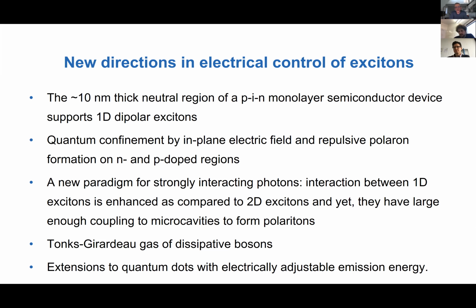If you have 1D excitons, the interaction is dramatically enhanced as compared to 2D excitons because there's only one extended direction, which increases the probability of overlap of the excitons dramatically. And yet, unlike 0D emitters, the oscillator strength coupling to the cavities is still strong, so that we expect to be able to see polaritons, particularly given that 2D excitons in this system show normal mode splittings exceeding 30 millielectron volts. Okay, and of course, one could also extend or modify the top gate so that one can make quantum dots, and actually an array of quantum dots, or an array of wires. So basically, all the aspects of electrical control will be at our disposal in this system.